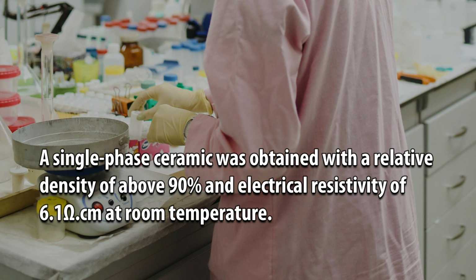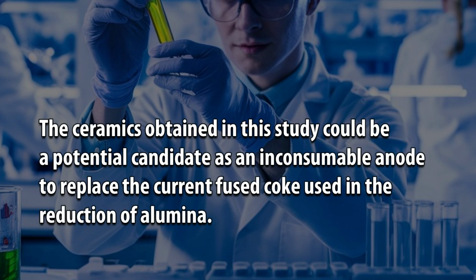A single-phase ceramic was obtained with a relative density of above 90% and electrical resistivity of 6.1 ohms centimeter at room temperature. The ceramics obtained in this study could be a potential candidate as an inconsumable anode to replace the current fused coke used in the reduction of alumina.